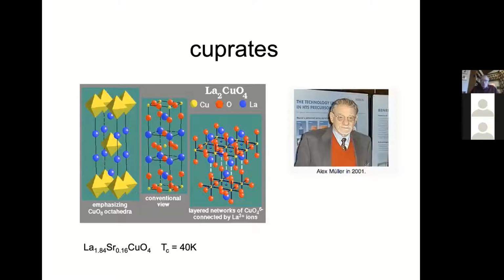So you can think about the cuprates in the same way. With the cuprates, you actually start with the classic one that Alex Mueller and Bednorz discovered, lanthanum 2 copper O4. You can look at this as CuO2 layers with La2O2 layers separating them. This starts out essentially as a non-conducting material that satisfies a valence rule, and with doping of strontium into the lanthanum layers, you're able to introduce holes into this material, and this becomes, of course, the start of the wonderful field of high TC materials.